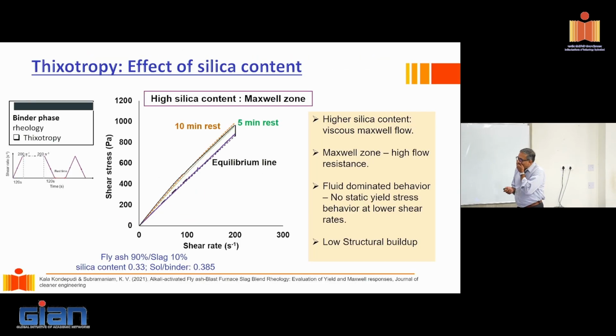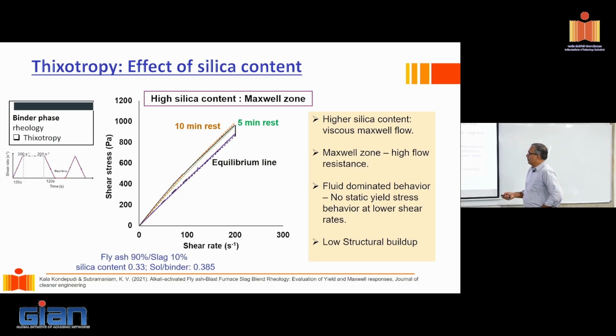The other issue that we have with this is this. Now, you've had this class on thixotropy. How do we measure thixotropy? We basically ramp it up, hold it constant, ramp it down, and take a small break, and then do a ramp up, ramp down, right? So what we're showing you here is the first ramp up, hold constant, ramp down, and then the subsequent ramp cycles. You see that nothing much changes, even if I give a 5-minute or 10-minute break.